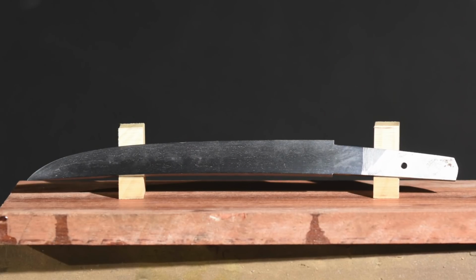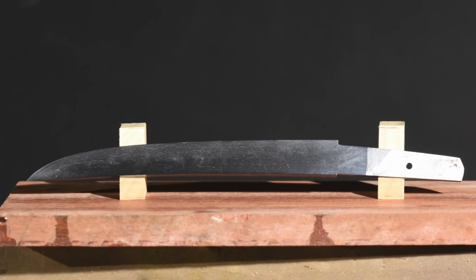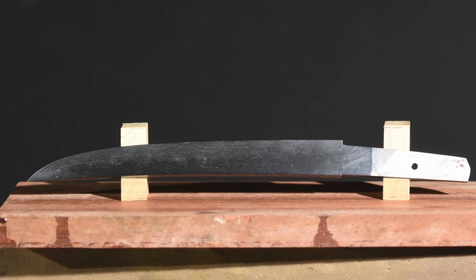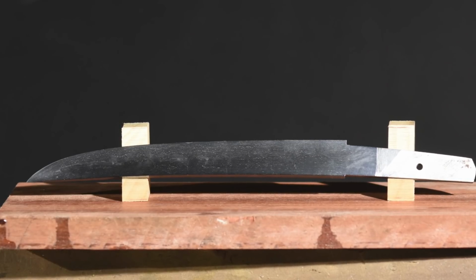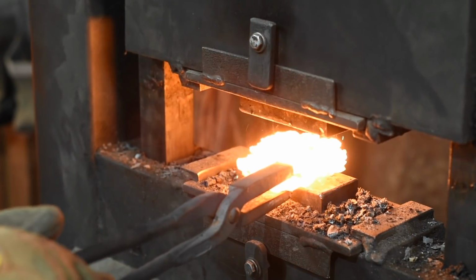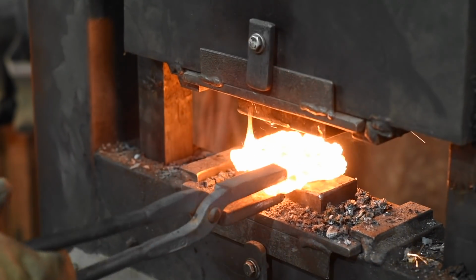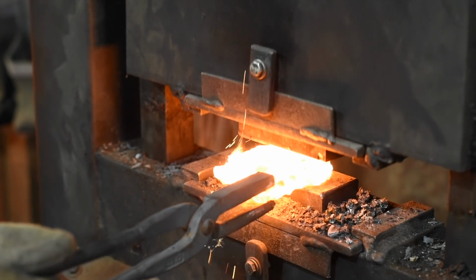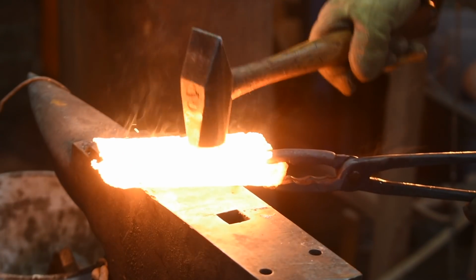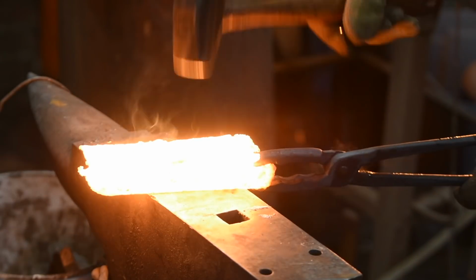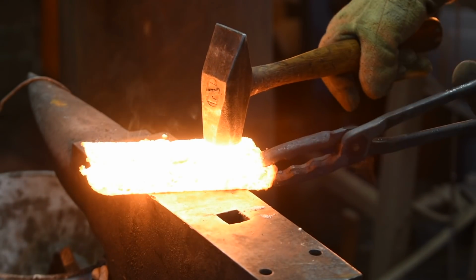Here, that lack of manganese allows the thicker part of the blade to retain enough heat during the quench that it didn't harden in those thicker sections. A second point is that the steel is probably relatively low in carbon. If I were to guess, it's maybe 0.6% carbon, and again, that's going to contribute to relatively low hardenability.